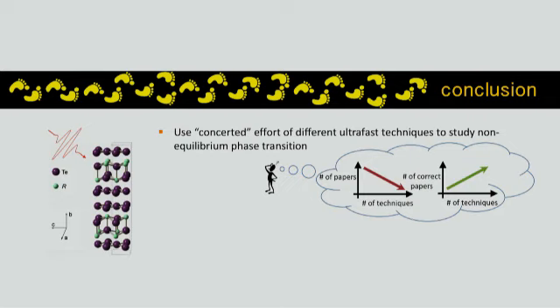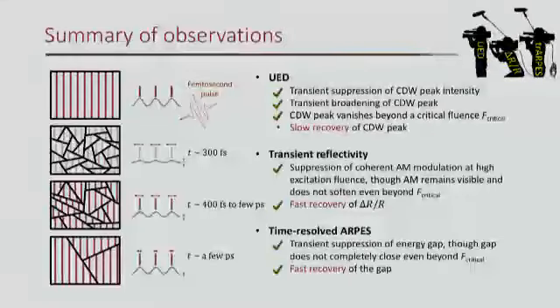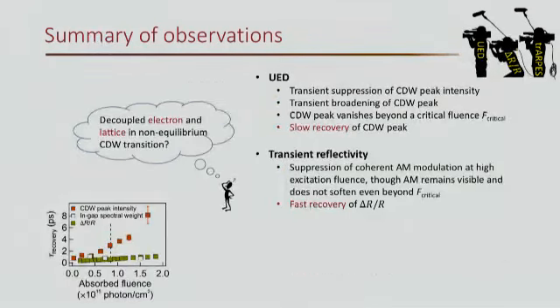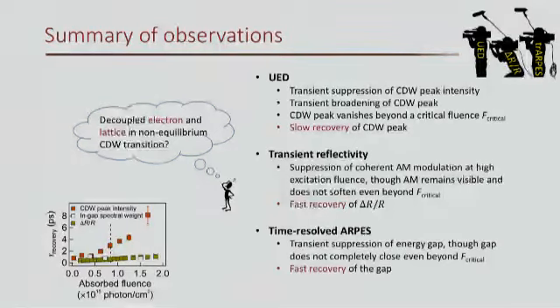Can you say again why you think that the electron cooling rate and lattice cooling rate are not decoupled? So there are really two regimes here. One is the regime of destruction of the charge density wave. In that regime, it can be decoupled, in the sense that it's very easy to excite electronic quasiparticles really fast, within maybe a few femtoseconds, 10 femtoseconds, and the lattice hasn't had the time to respond.